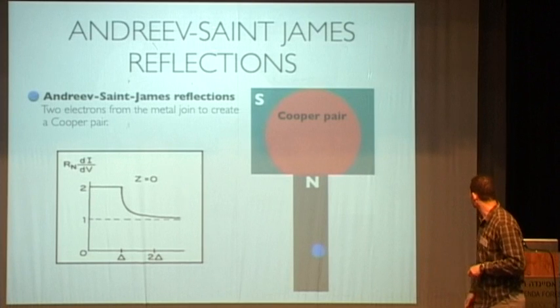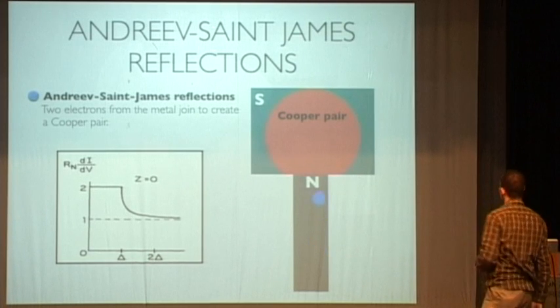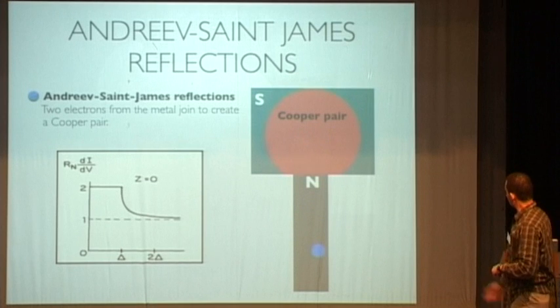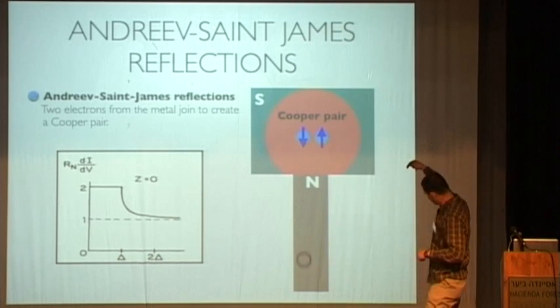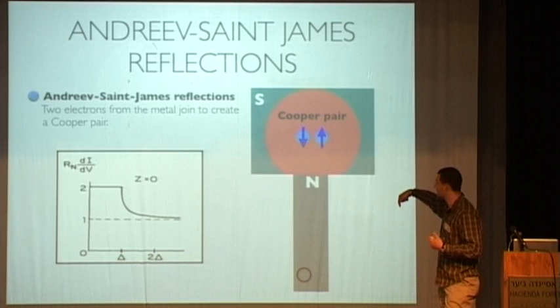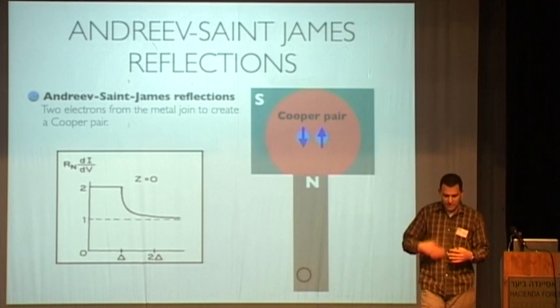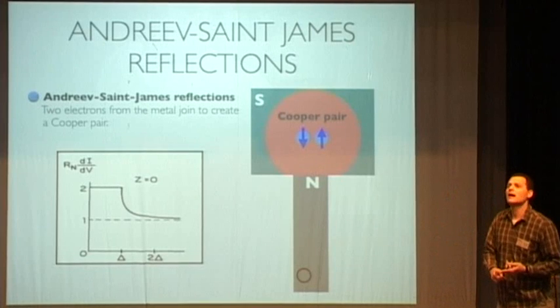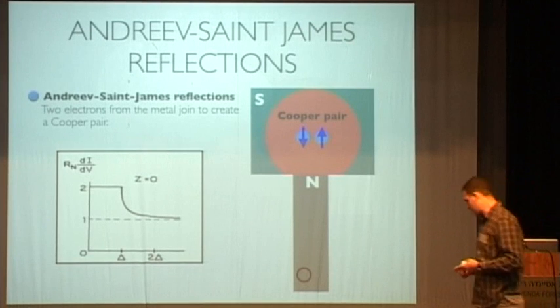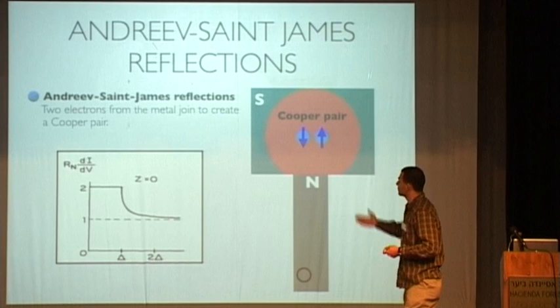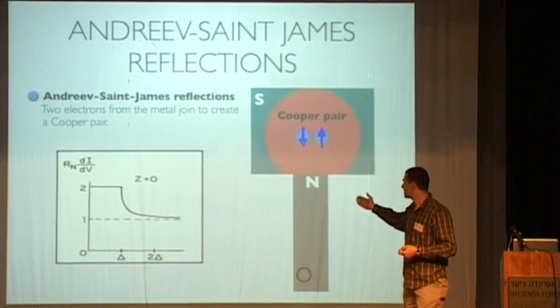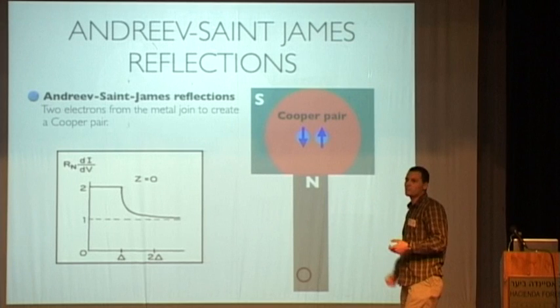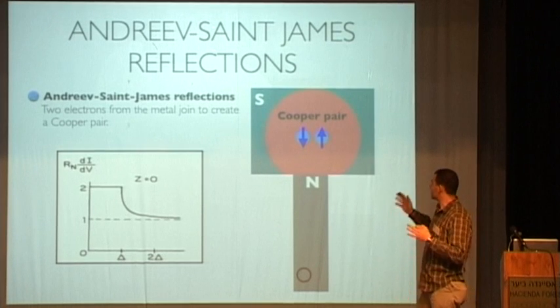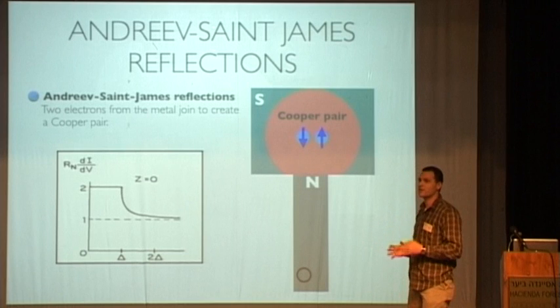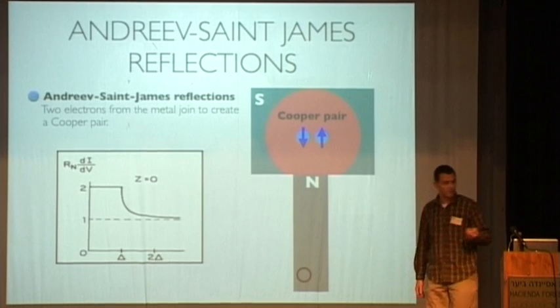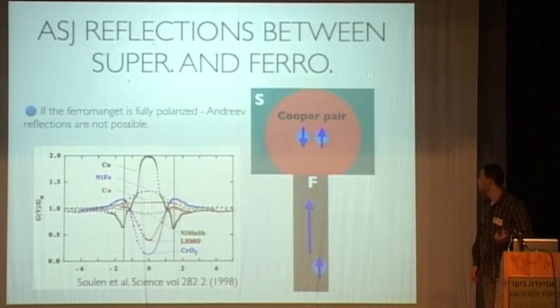So you can see in this simple cartoon here, an electron coming towards the superconductor, and an additional hole is reflected back. So you inject one electron, you get double the charge, because another electron is injected as well. So in terms of conductance, you get double the conductance as compared to the normal state. So this is a fingerprint of this mechanism, Andreev reflection. And this will be important for our work.